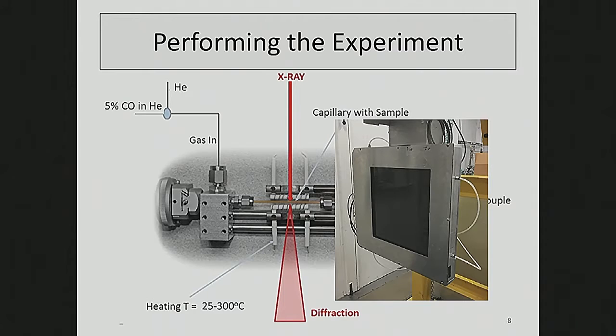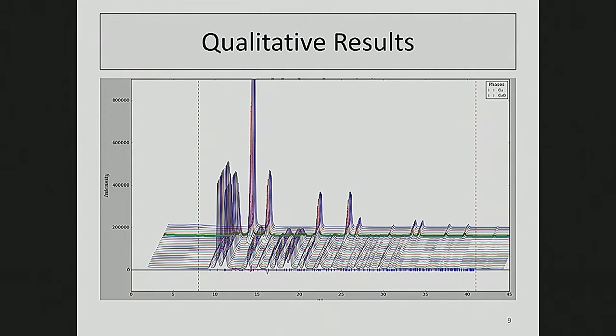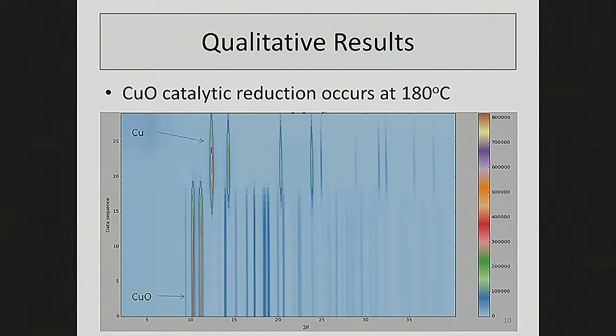You can also look at not only just the image, but also the averaged intensity. So you can see these copper oxide peaks change here at about 180 degrees Celsius into the copper peaks, seen a little bit better in this topological map. So you can see the copper oxide peaks disappear just as the copper peaks appear, which I won't tell too much about because that's the next group's talk, which I'm sure they'll do a great job of talking about.